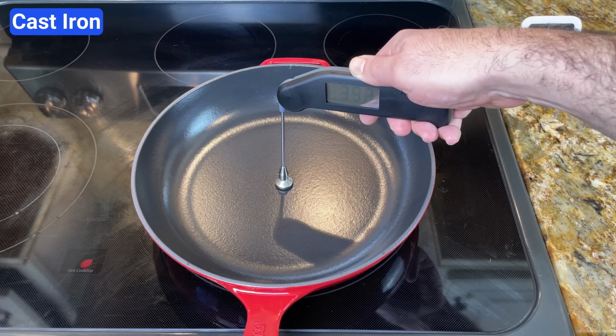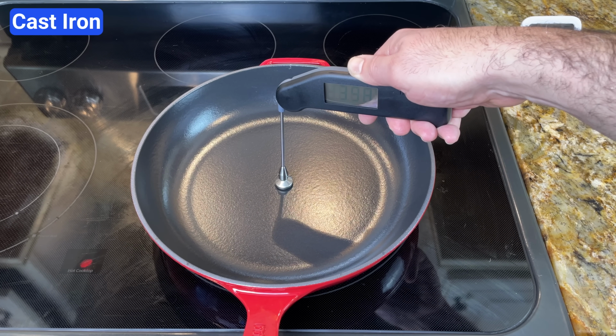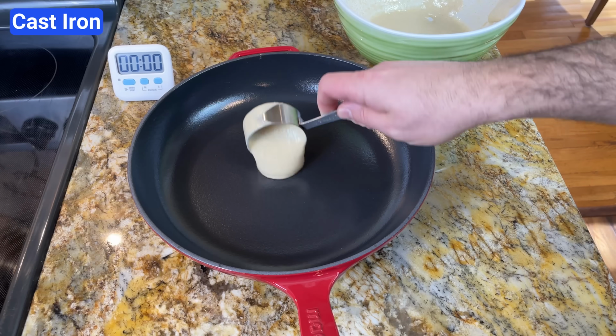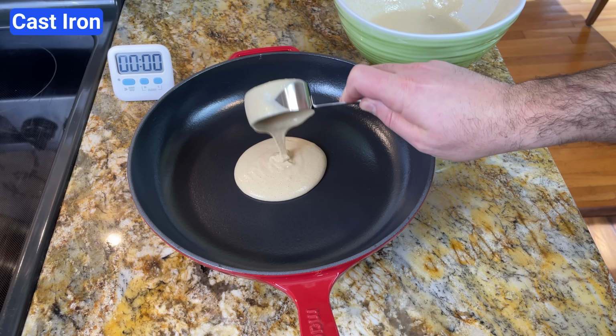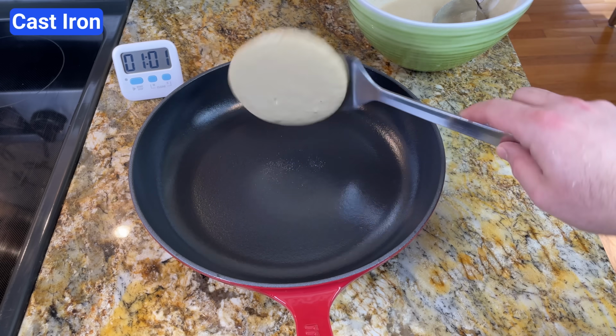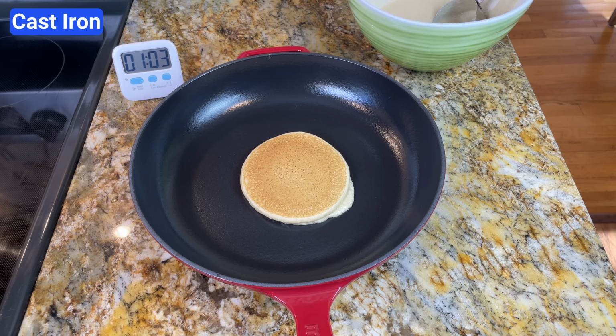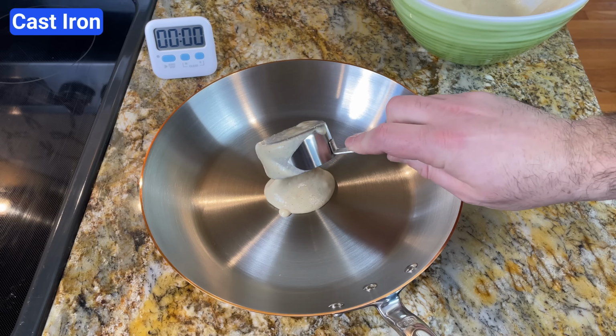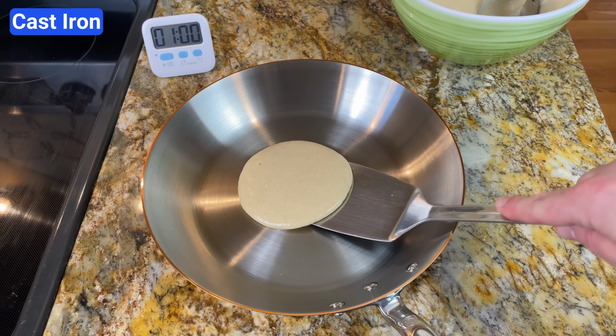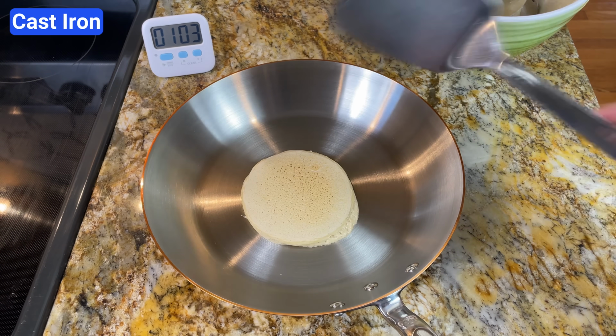I heated the cast iron pan again to 400 degrees Fahrenheit, took it off the heat, and added a third cup of pancake batter. Even though there was no heat source, the pan retained enough heat to cook the pancake perfectly. I did the same thing with a copper pan, and the pancake barely cooked at all since copper doesn't retain heat at the level of cast iron.